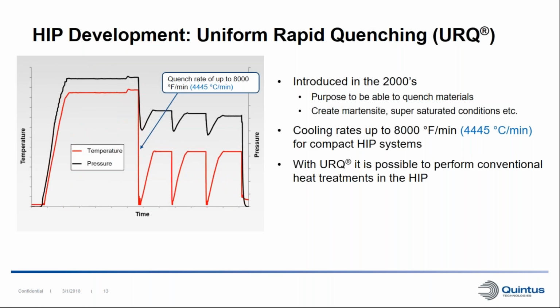In the 2000s, we took this technology a step further, where we're looking at even higher cooling rates. And the purpose of this invention was to be able to quench materials, to actually be able to create your martensite or supersaturated condition in the HIP. So it would be possible to actually do conventional heat treatments in the HIP step.